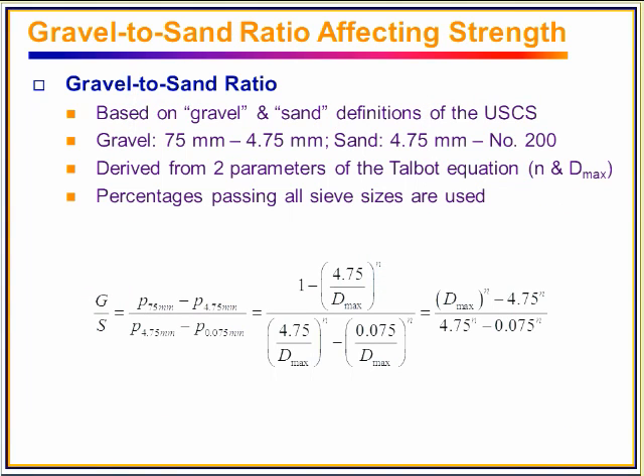Once we have all the gradations, we categorize the gradation based on the previous methods to calculate the quantitative gradation parameters, and then we try to correlate those gradation parameters to shear strength. After some statistical analysis, we found that this parameter, gravel to sand ratio, calculated using this formula, has a much better correlation with shear strength properties.